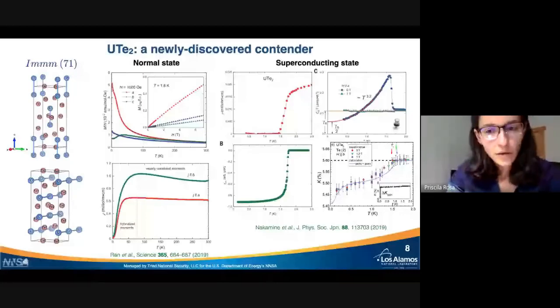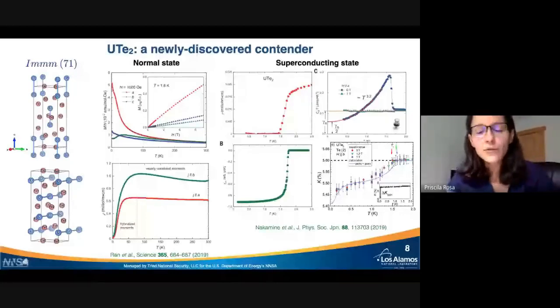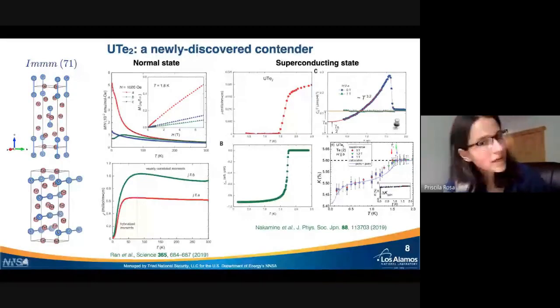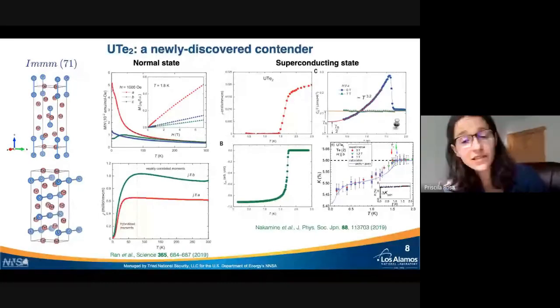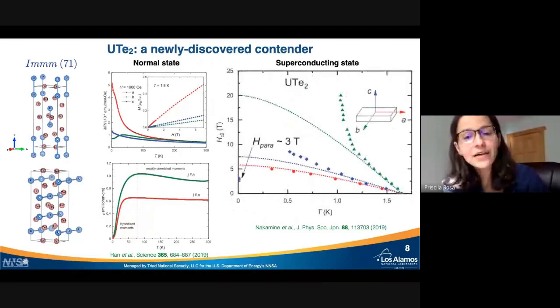But unfortunately, only data along the B axis is known so far, so there's still a lot to be done there as well. But I think the main point here is that this is a new material. Even though it has a low TC, it seems to have properties that are not consistent with a simple spin singlet material. And this is really clear in the upper critical field plot.